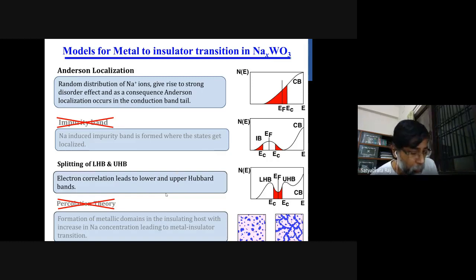Or even if you take the 5d orbital, the 5d can have 10 electrons, and for 10% sodium doping, that means 0.1, the system should behave like an insulator, and for less than that the system should be metallic. That means for integral doping, the system should be metallic. So the Mott transition is not favorable in this sodium tungsten bronze. So it is the Anderson localization which is preferable.